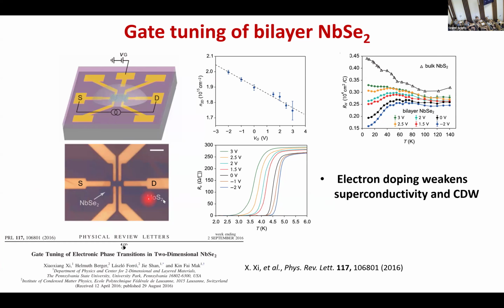So what they are doing in this paper is that by going down to a monolayer or bilayer, now you have not so many carriers, so that you can tune the sample relatively easily, so they can use this ionic liquid gating. The liquid gating can offer you a large tunability, roughly 10 to the 14th per square centimeter. So by doing so, you can tune the TC in a larger range.